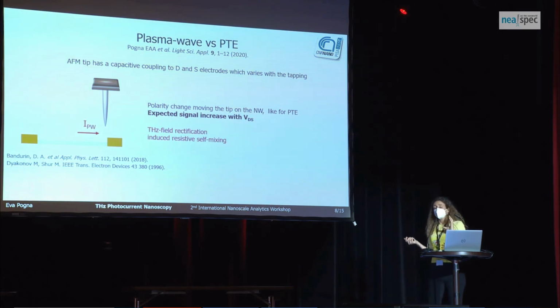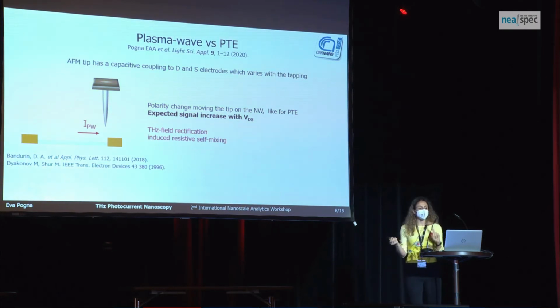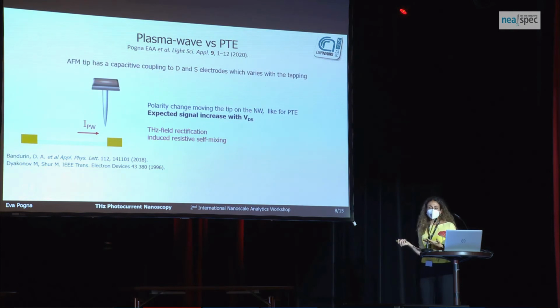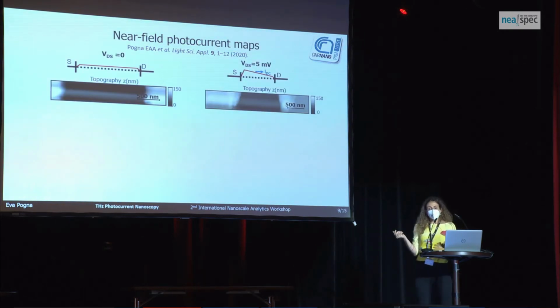We can distinguish this effect from the photothermoelectric effect because in this case we expect to see a variation with the bias, because the current will increase the asymmetry between the electrodes and enhance this response. So let's go to the data. We have tried tons of nanowires with different length and different distance between the lateral gates that we use to tune the charge carrier density in the nanowire. So, the capability of tuning the carrier density within the nanowire.